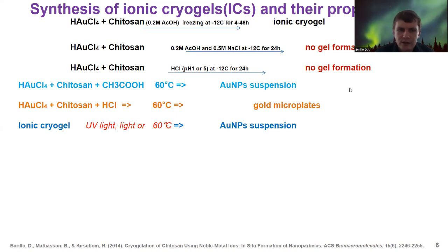So if we incubate the reaction mixture of chitosan with tetrachloroauric acid at 60 degrees centigrade, it leads to formation of a gold nanoparticle suspension. And if we do the same but with chitosan which was dissolved in hydrochloric acid, then it leads to formation of only gold nanoplates.